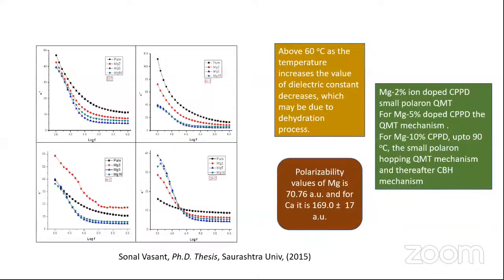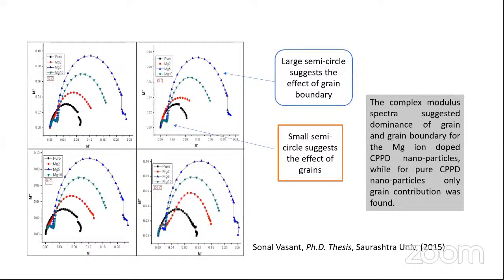Again, the same type of situation is shown: the large semicircle shows the grain boundary effect, and the small semicircle shows the effect of grain. The pure samples have a grain effect, and the doped samples have a grain and grain boundary effect. So complex modulus spectra suggest dominance of grain and grain boundary for magnesium ion doped CPPD nanoparticles, while for the pure CPPD nanoparticles, only the grain contribution is found.